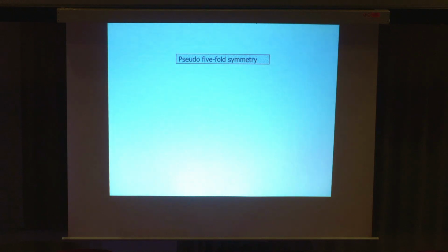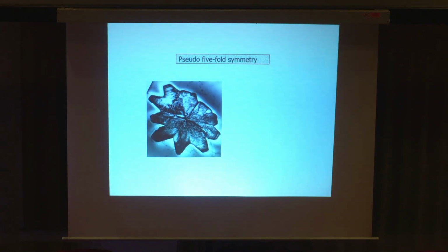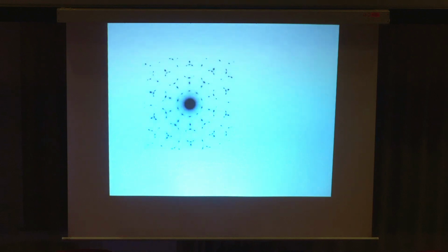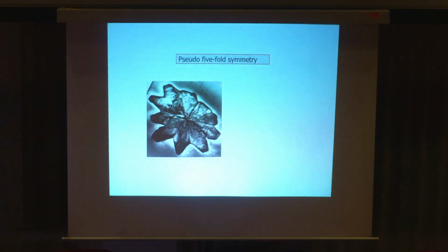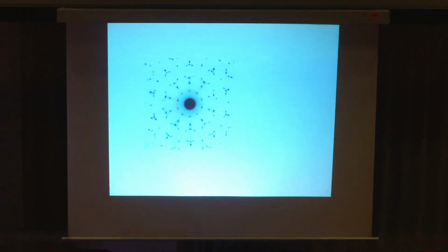Now I show you, here is a crystal with a pseudo 5-fold symmetry, like the diamond crystal. This is a crystal in the aluminum iron system, and it is very large. You see it by optical microscope, very large. And again, the same thing. And if you take a diffraction pattern from the center of all 5 of them, then this is what you'll get.